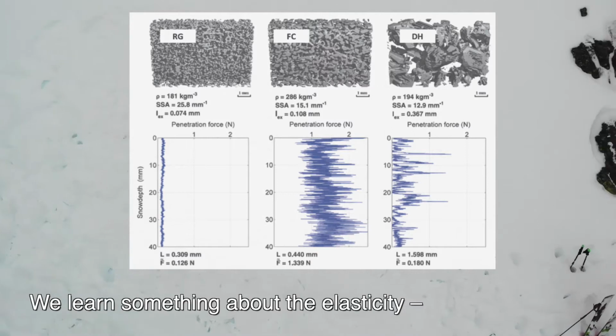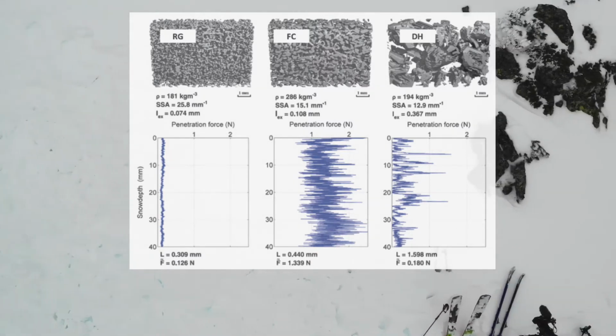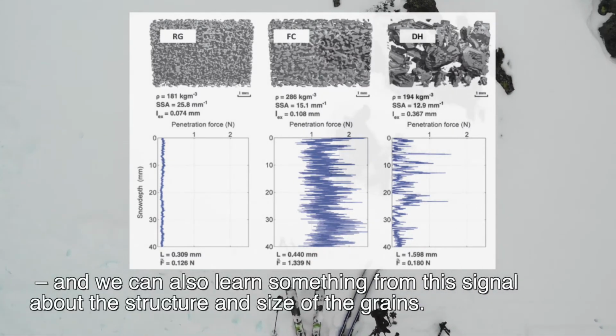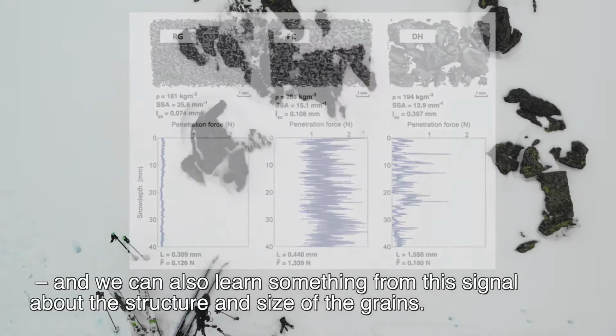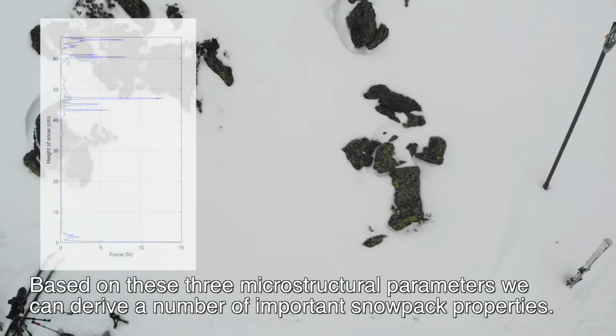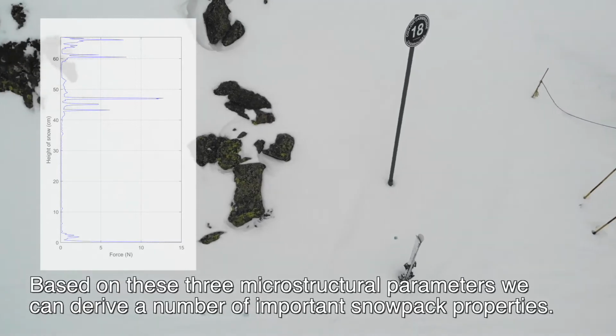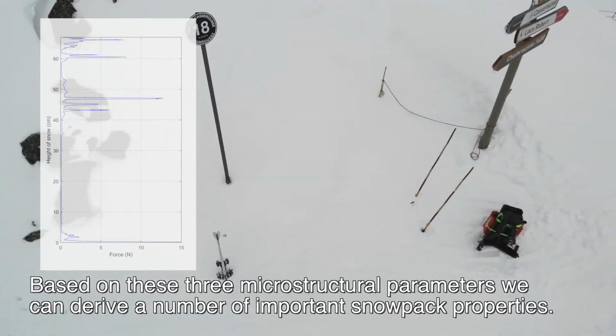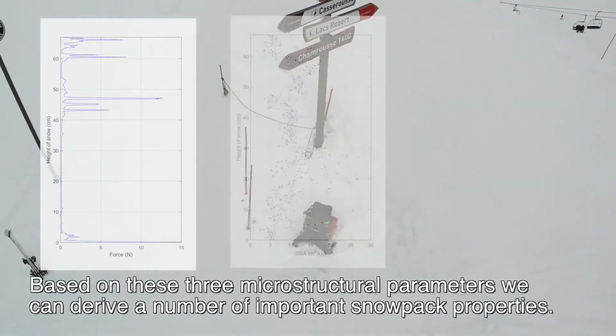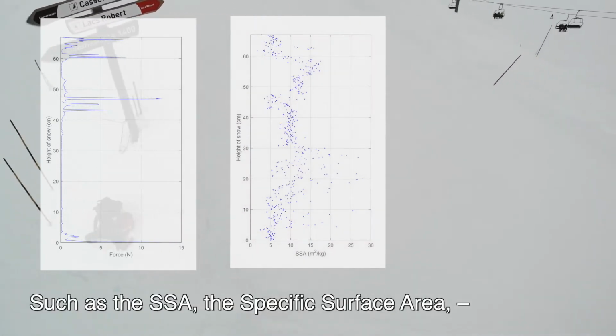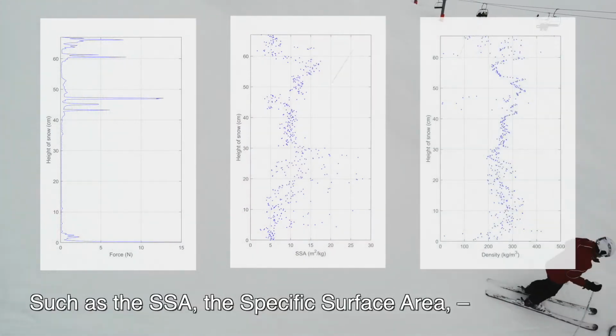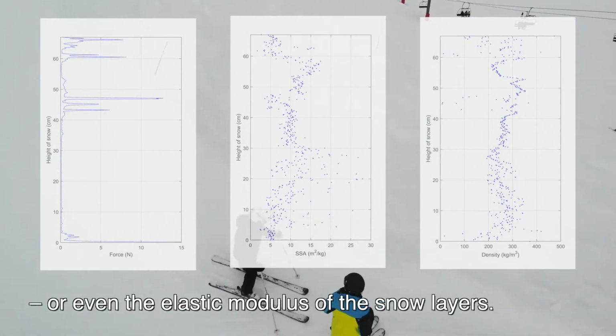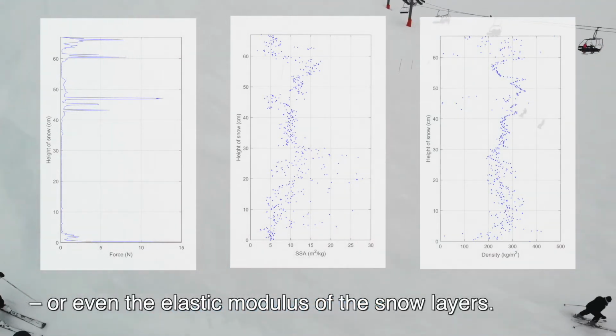So we learn something about the elasticity, and we can also learn something from the signal about the structure and size of the grains. Based on these 3 microstructural parameters, we can derive a number of important snowpack properties, such as the SSA, the specific surface area, or the density or even the elastic modulus of snow layers.